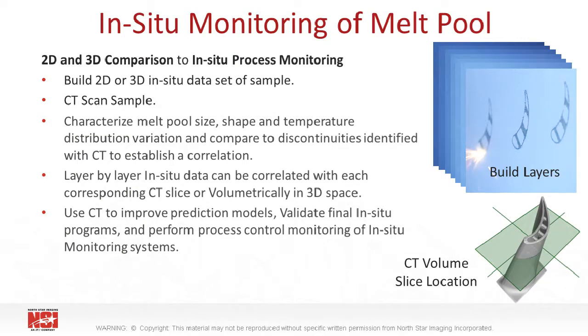In situ monitoring technology continues to make advancements in numerous AM processes. A great way to initially evaluate and then improve upon the effectiveness of the process is by understanding the correlation between the in situ monitoring of the AM part and the results from a CT scan of the part. Layer by layer data from in situ detectors can be spatially correlated to CT scan data to provide tweaking of the process to improve prediction models of discontinuities forming. Basically, if in situ monitoring of the melt pool predicts a porosity of a specific size is likely to occur at a given location within the build, there should be a direct correlation for that indication within the CT scan. Once this correlation has been optimized, CT can be used to validate final in situ programs and used to perform process control monitoring over time.